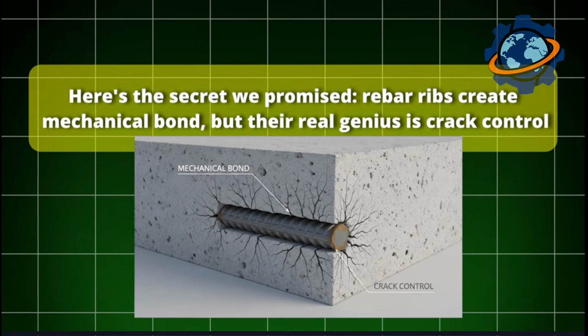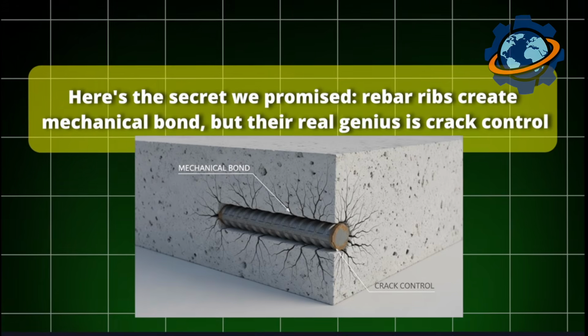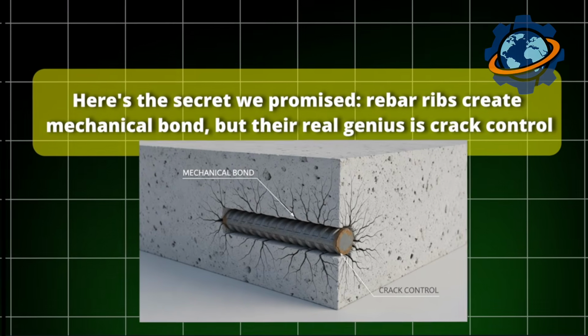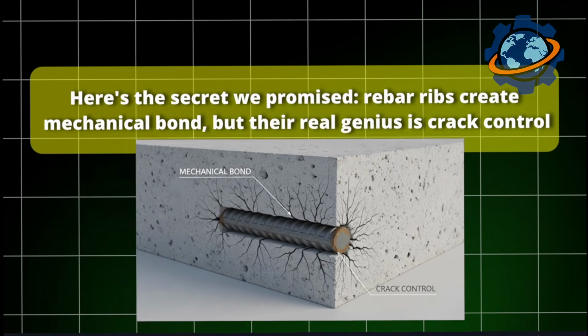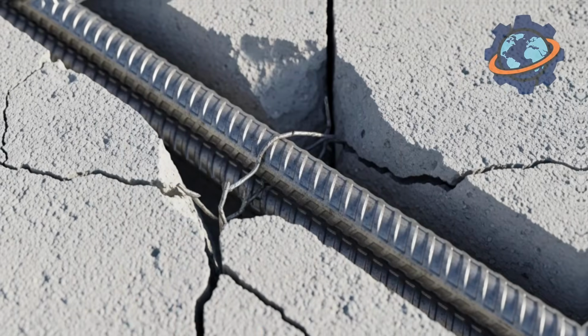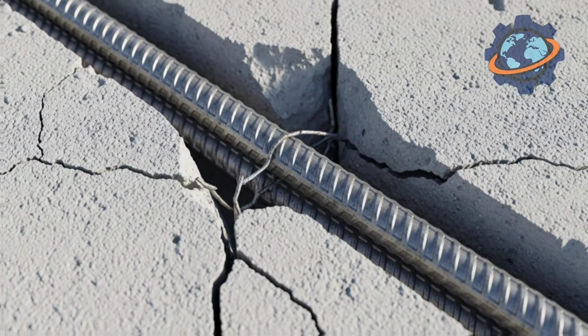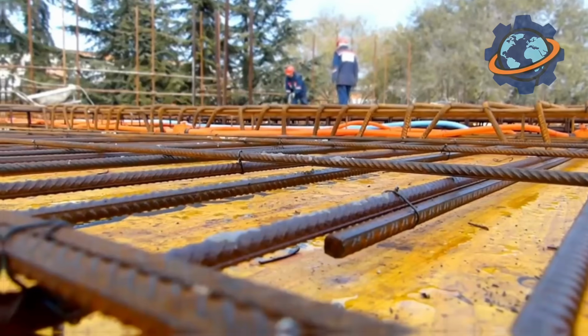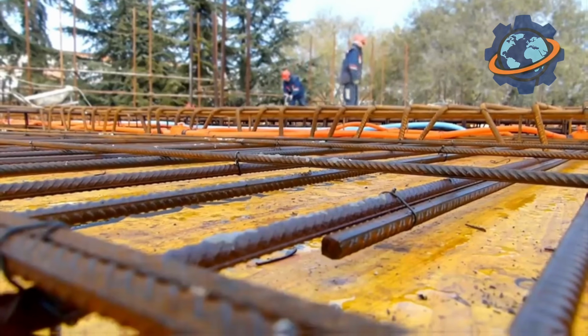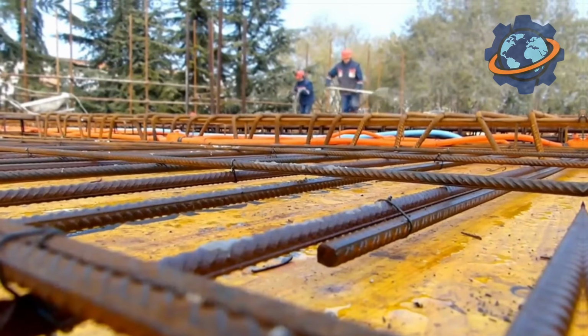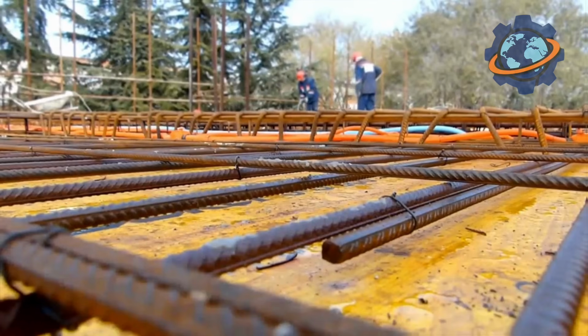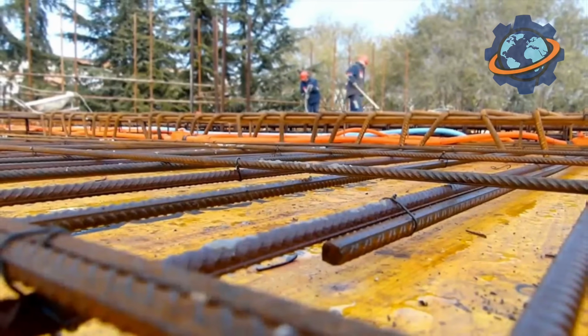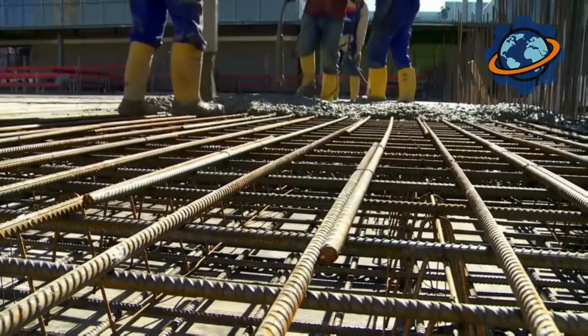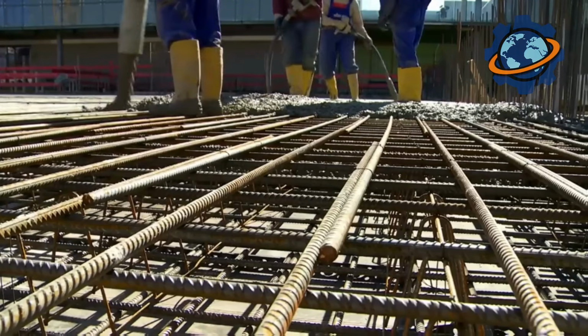Here's the secret we promised. Rebar ribs create mechanical bond, but their real genius is crack control. Concrete always cracks. Thermal expansion, settling, loading all cause microscopic fractures. Smooth rebar allows cracks to propagate, widening until failure. Ribbed rebar intercepts cracks, distributing stress across multiple ribs, preventing single crack from becoming catastrophic failure. Those ribs transform concrete from brittle material into ductile system that bends before breaking.